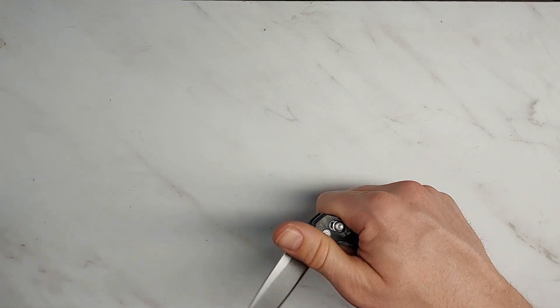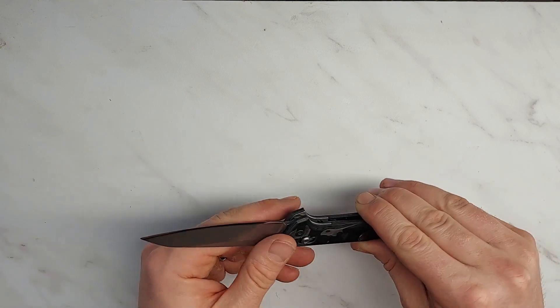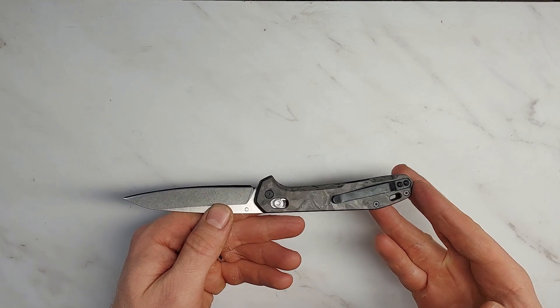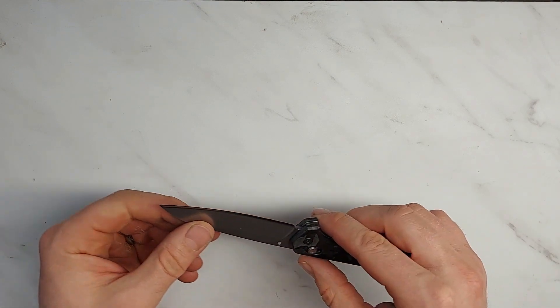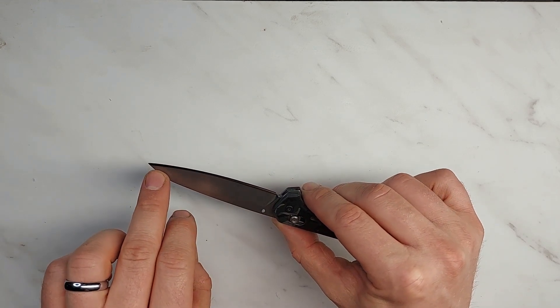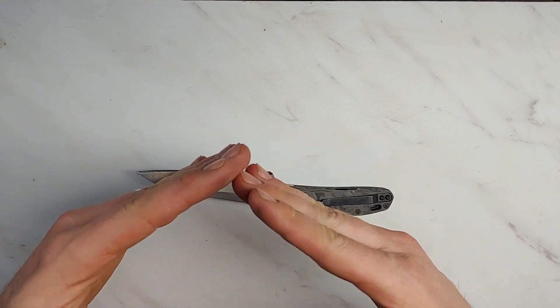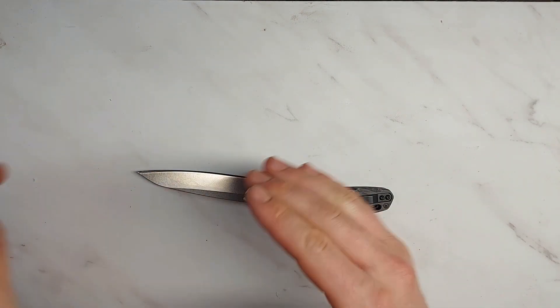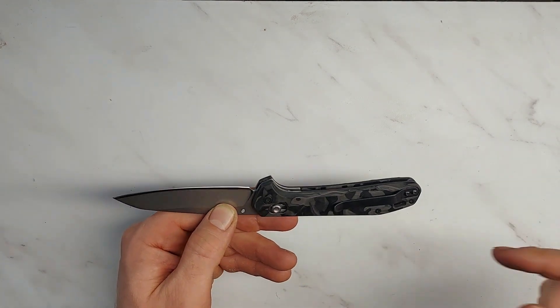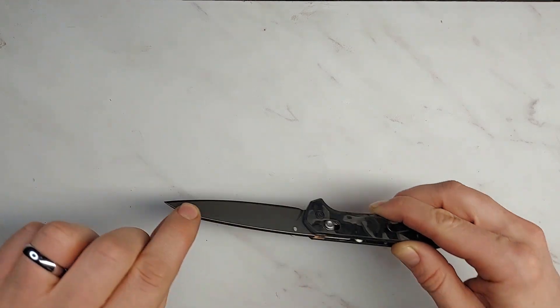When I got this knife, the edge was very steep — almost like an axe. I did my edge retention testing and it only scored 125 cuts. I thought maybe that was a blade geometry issue, so I reprofiled the entire edge to a more shallow appleseed edge and redid the testing. It only made 75 cuts — so removing material from the shoulders of the blade actually made it worse, not better.